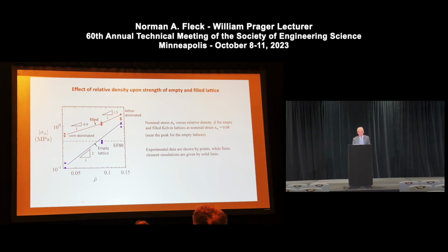However, when you increase relative density, one sees that the empty lattice is now significantly stronger on this log-log scale, significantly stronger than the rubber, and consequently the lattice dominates the response. So it's somewhat complicated, this behavior, because whenever you fill the lattice, you do two things. You add the strength of the core, the EF80 core, but you also impose incompressibility. And this is the net effect.